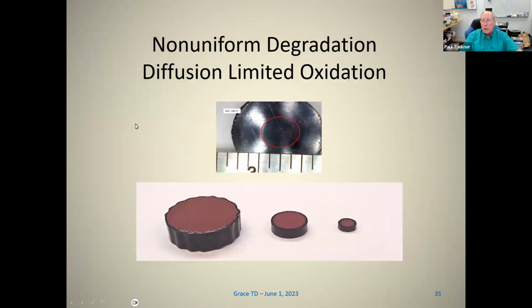The third thing is mode of degradation. So in this case, where I noted previously that if you had specimens with the same shape factor but different diameters and heights, you should get the same percent retained sealing force.